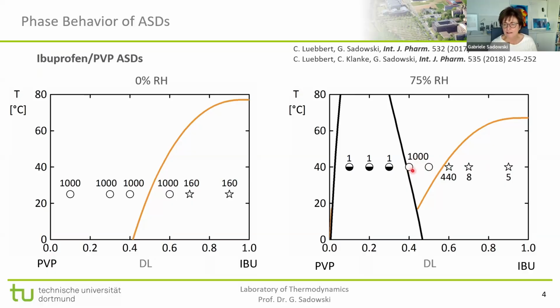So surprisingly, for the pharmacists, it was not the very low drug load that kept the system stable, but the ones in the middle. And this agrees with our predictions.